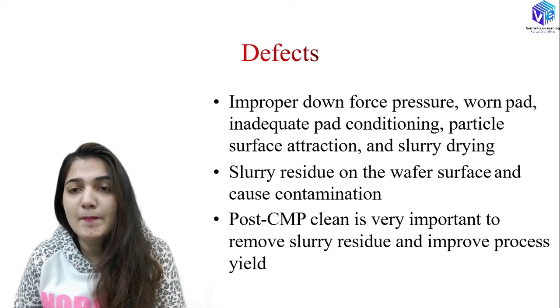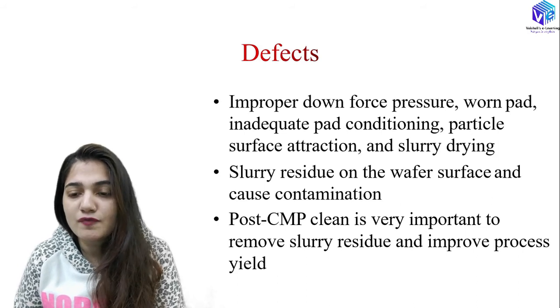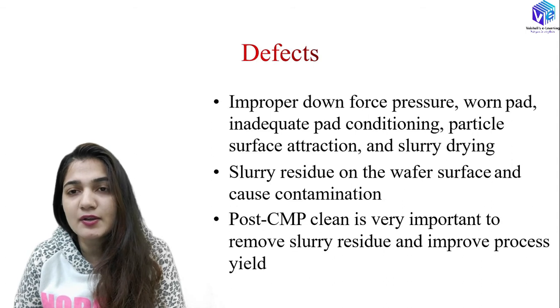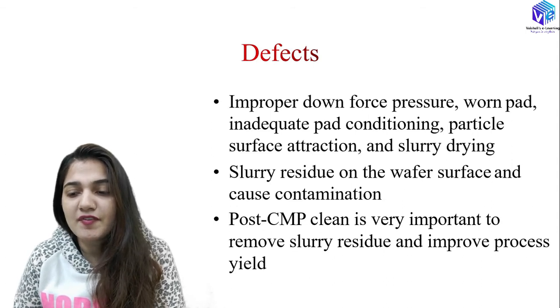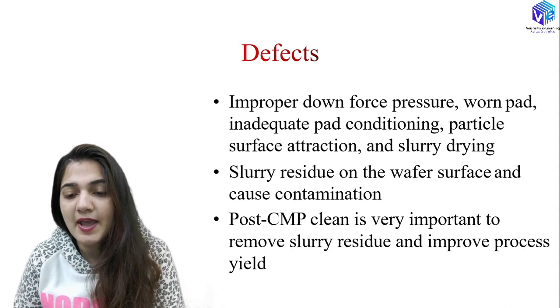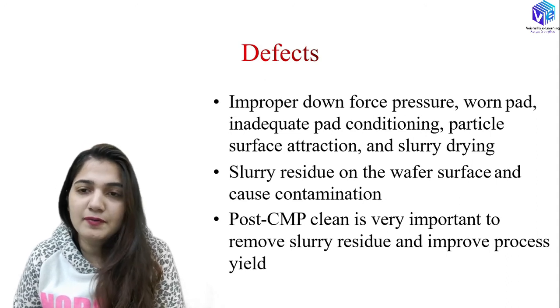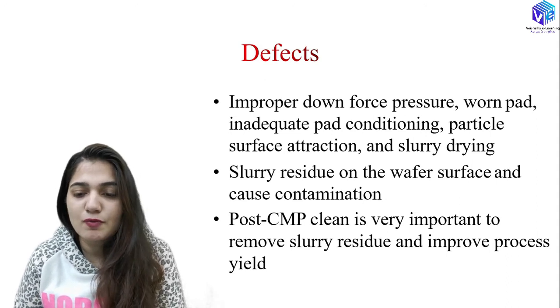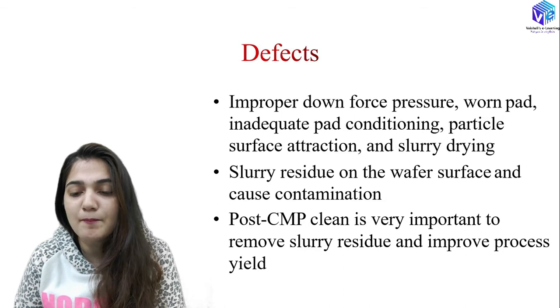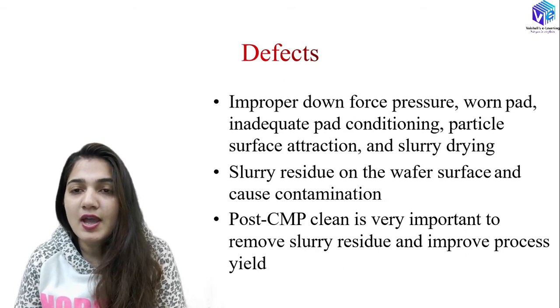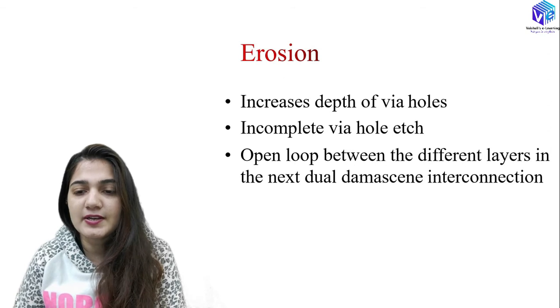Improper downward force, worn-out pad, inadequate pad conditioning, particle surface attraction, and slurry drying are all main causes of defects on the wafer. Slurry residue on the wafer surface also causes contamination. Post-CMP cleaning is very important to remove slurry residue and improve process yield.